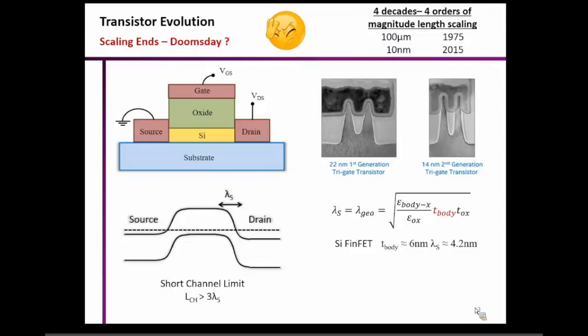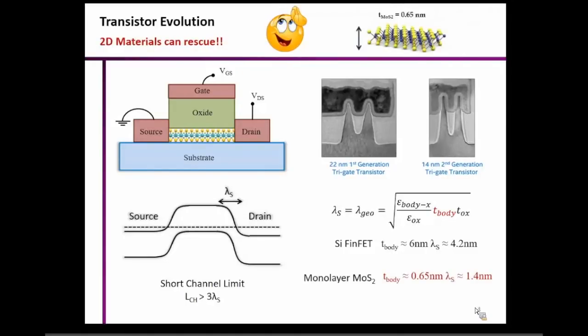And this is exactly what makes these 2D materials very interesting, because a monolayer of MoS2 is only 0.65 nanometers thick, which means you can scale the thickness by a factor of 10. That allows you to go for a few more technology nodes, because now you can scale the devices down to maybe 5 nanometer or even 3 nanometer nodes. So that's the advantage of using these 2-dimensional materials.